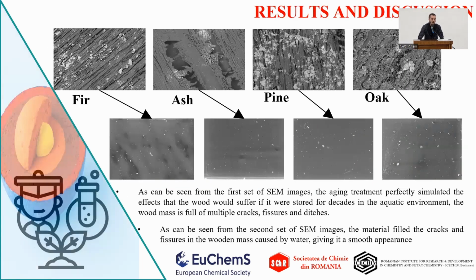Some results and discussion. As can be seen from the first set of SEM images, the aging treatment perfectly simulates the effect that the wood would suffer if it were stored for decades in the aquatic environment. The wood mass is full of multiple cracks, fissures, and ditches. And from the second set of SEM images, the material fills the cracks and fissures in the wood mass caused by water, giving it a smooth appearance.